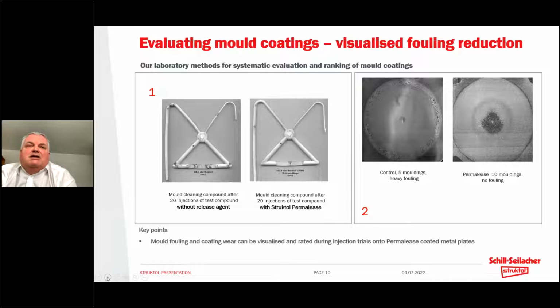If we look then in detail a little bit more at some of the examples that we can see from method 1, the mold cleaning, if you like, and pickup of mold fouling. On the left-hand side, we have a cleaning compound after 20 injection cycles of a mold without a release agent. So the mold was a clean mold. We injected a rather mold fouling compound designed to create a degree of mold fouling 20 times and then cleaned the mold. And we can already see with our light colored, almost white cleaning compound, a degree of mold fouling at several points on that molding, where the mold flow changes direction, where the two streams come together to combine on the bottom areas. We pick up quite a severe or a notable degree of mold fouling with the dirt